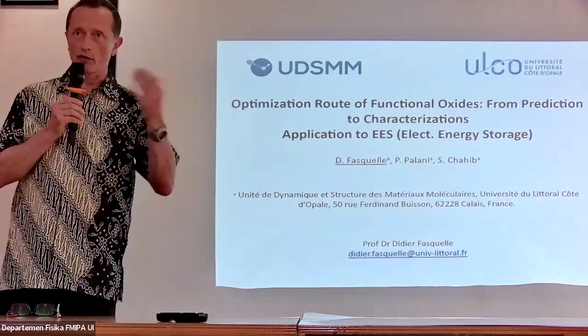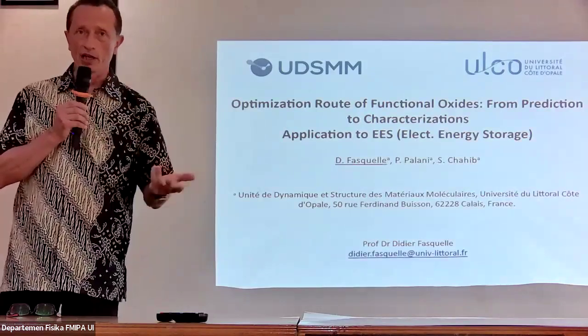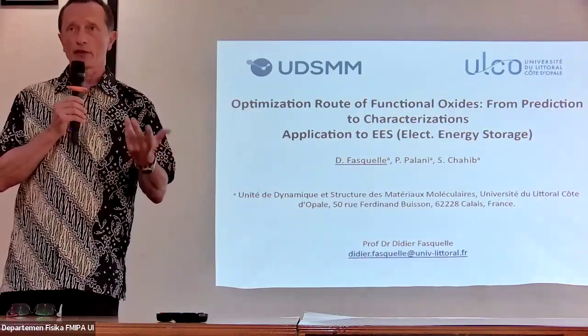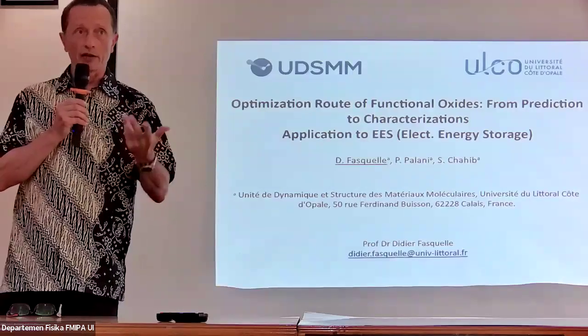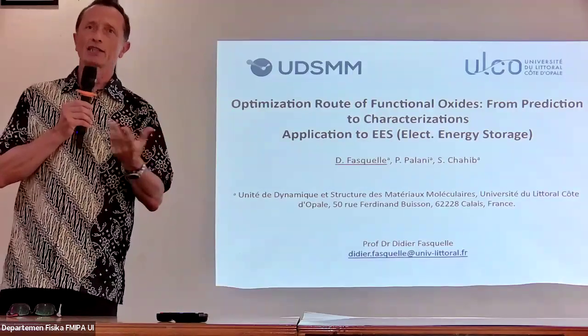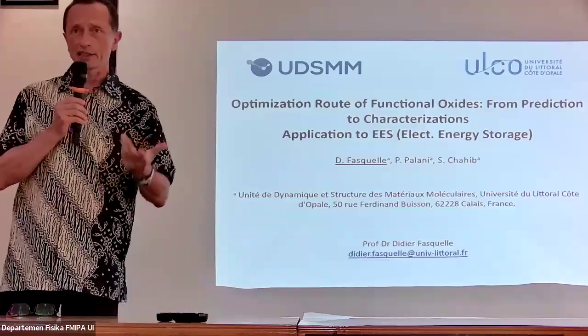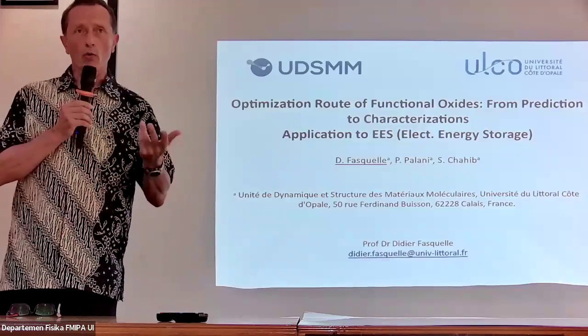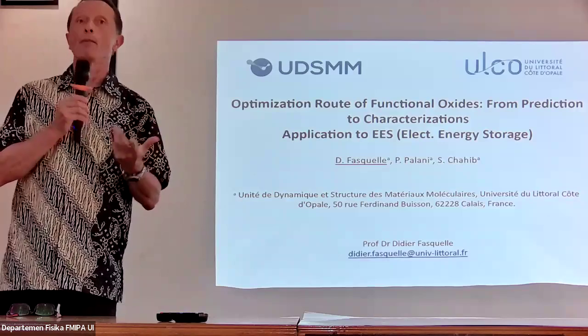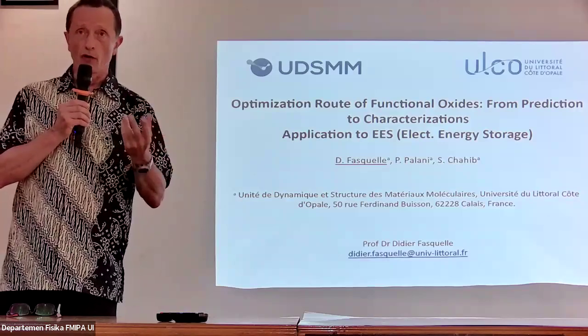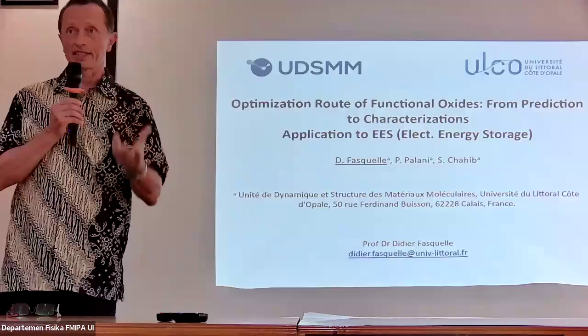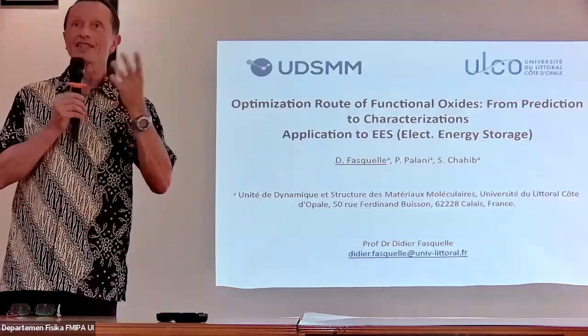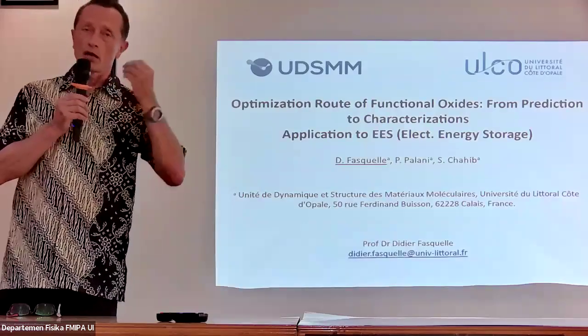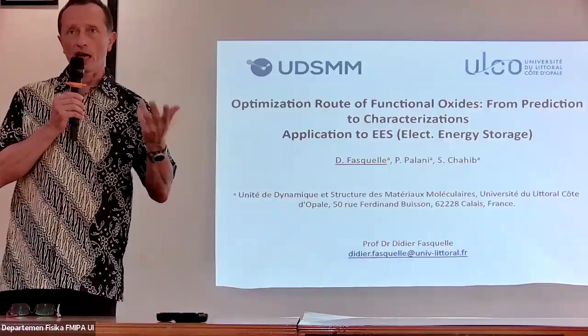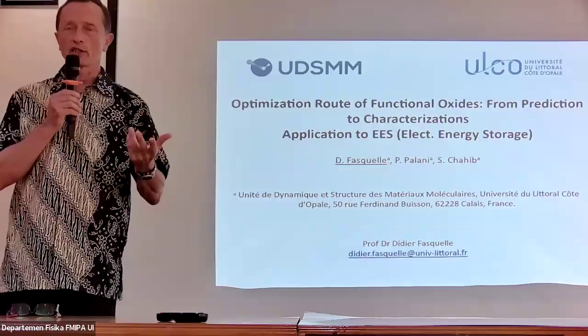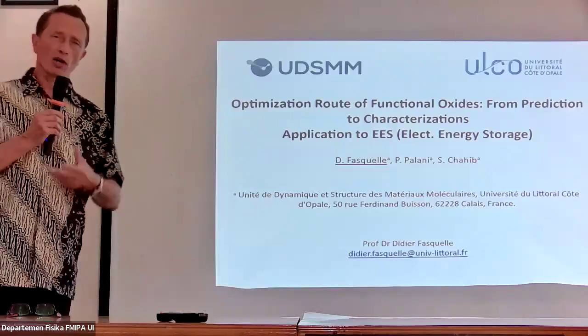After that, you can decrease the scale, and you can deposit by different techniques. You have physical techniques, you have chemical techniques. You can deposit some thin films. Thin films in scientific literature means that your material has a thickness lower than 1 micrometer. So for the thickness of thin films, we are talking about nanometers, generally from 50 nanometers to 500 nanometers.